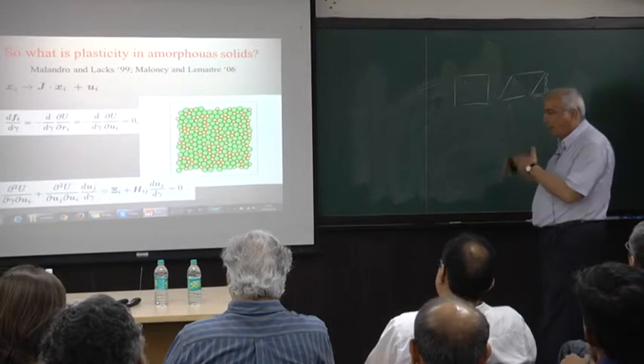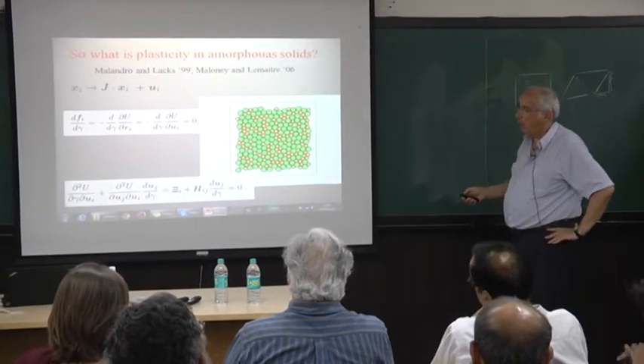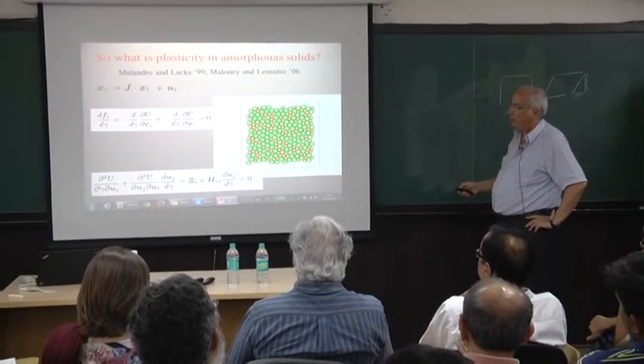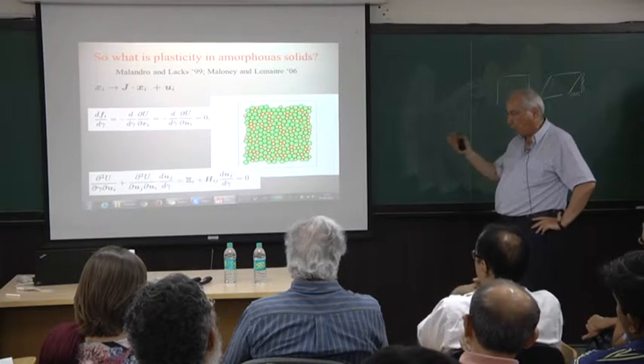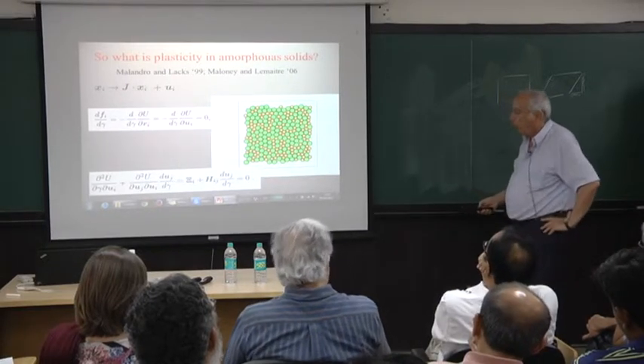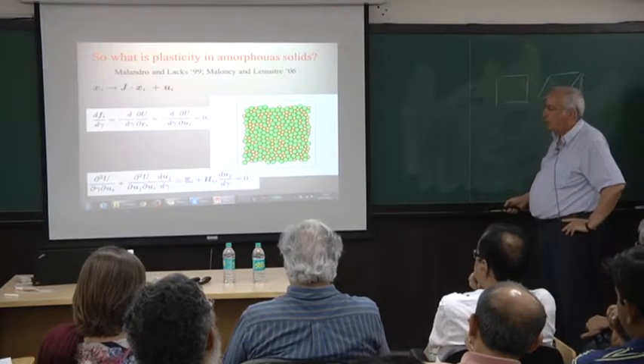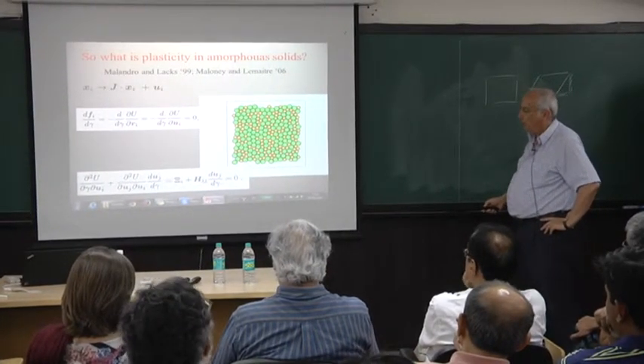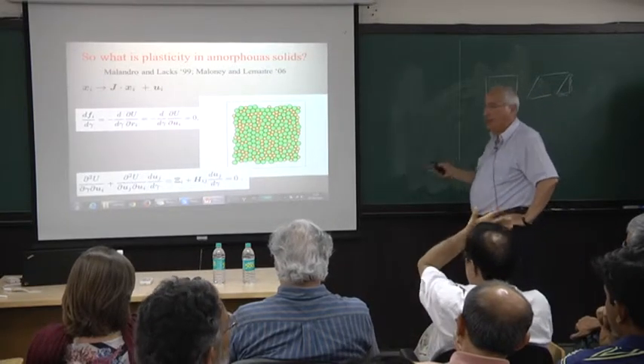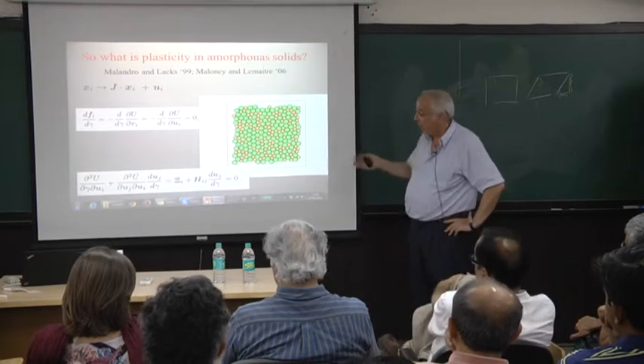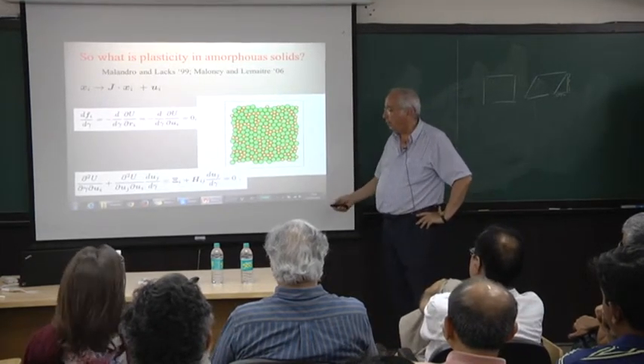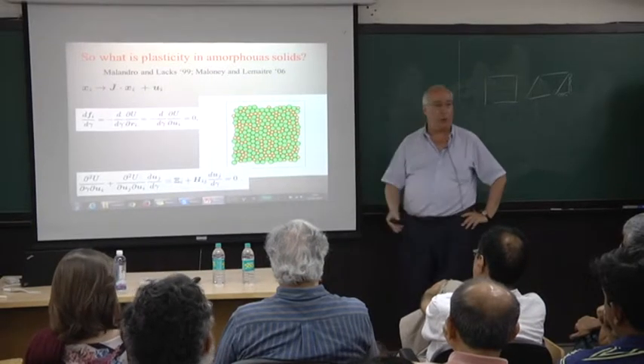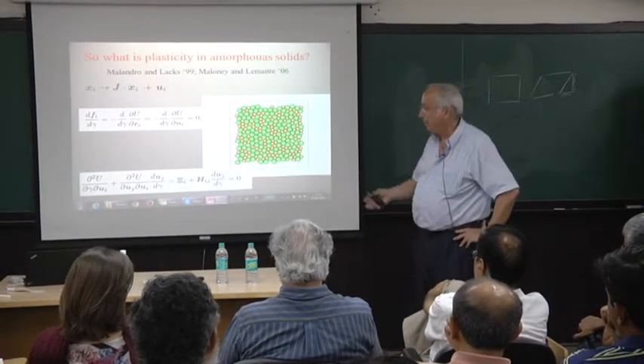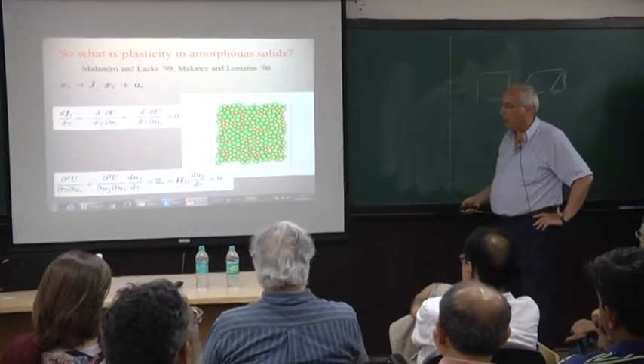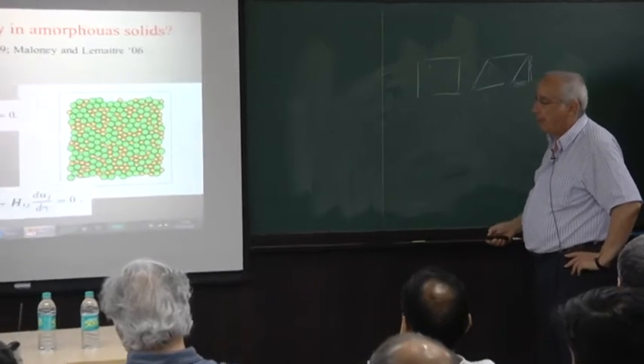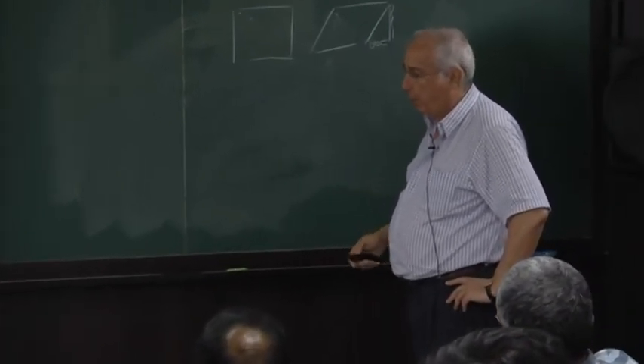So I can begin to understand what are the processes that are occurring once I have decided to do an affine transformation, and I'm looking at the non-affine response, and I want to sort of understand what it does. So if I assume that this H has no zero eigenvalue, I can, of course, invert. Now, this assumption is dangerous. And the danger is that you all know there are going to be values of gamma where eigenvalues of H are going to zero, and then this is going to be an instability and what we call a plastic event. So plastic events are going to be understood as eigenvalues of the Hessian matrix going through zero.